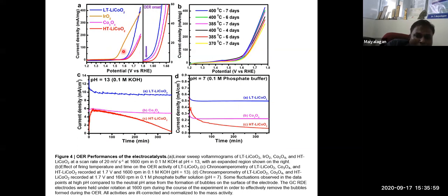Though iridium oxide is a very good catalyst at lower potential range, iridium oxide is very expensive. That is the idea. We want to change it. We tried cobalt oxide. You see the cobalt oxide peak and lithium cobalt oxide peak. This pink one is the cobalt oxide, and then the lithium cobalt oxide. You see it is 2 times higher for the lithium cobalt oxide. So this is how it has been changed. And at higher potential, the performance matches with the iridium oxide.